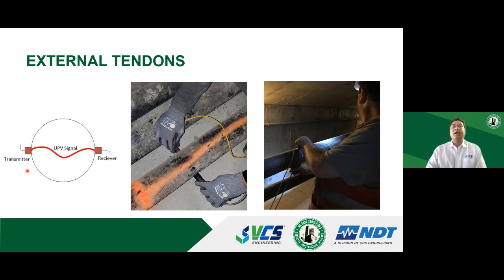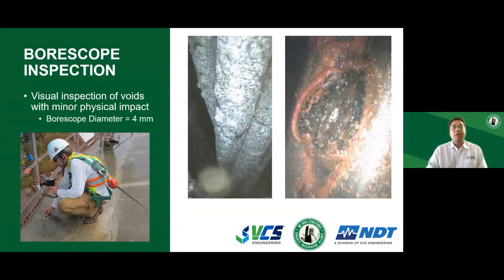Once you have identified the extent or the location or the areas of potential defects, then we need to visually confirm if the defect is actually present or if it was a false positive. And one way to visually confirm the results of impact echo testing is using a borescope. In this, we make an opening in the concrete, we open up the metal duct and we put a pinhole camera into the metal duct to see if the voids exist or not.